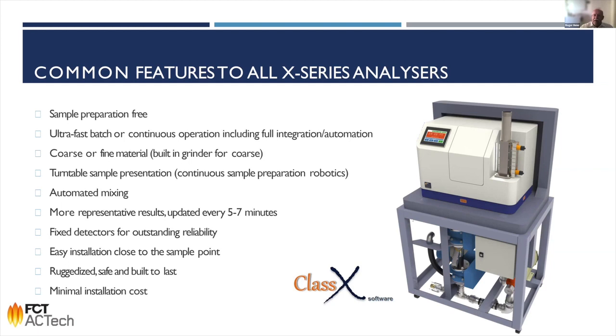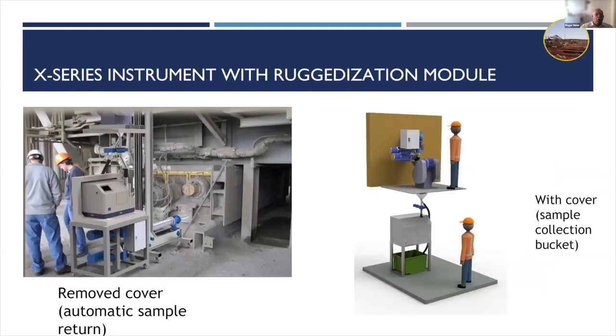The machine can be put in a ruggedization kit to isolate it, so that you have a constant temperature. So also the equipment does not require a laboratory container in the field. It can be simply placed next to the process as long as there is no direct sun or rain hitting the machine. Here you see one typical installation of our FLX, the free lime analyzer. All fine materials like raw meal, cement, etc. can be measured directly. In case of clinker, we use a primary crusher to reduce particle size, and we have an integrated mill inside to have a proper representation of the sample.